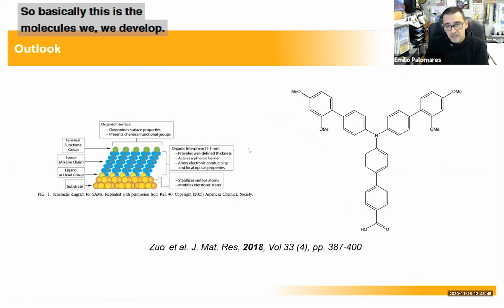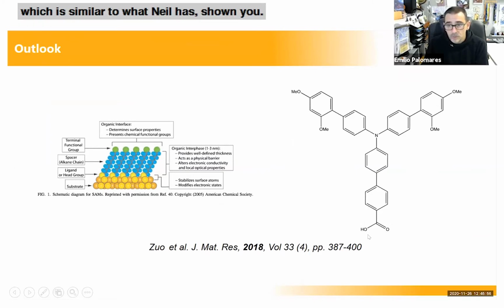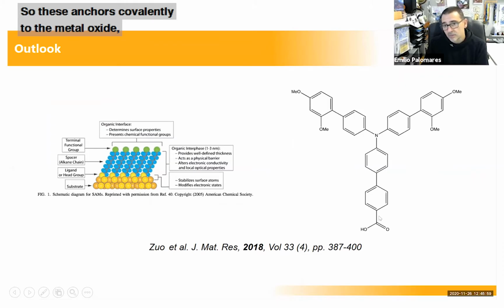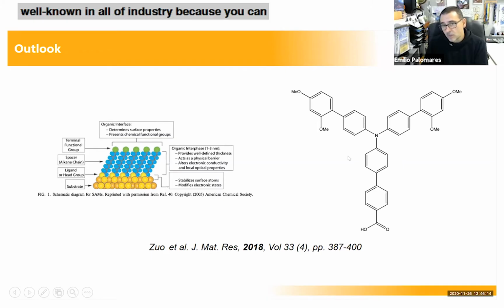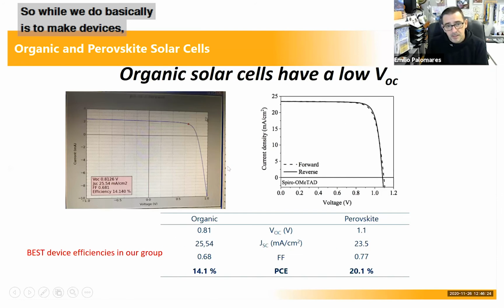So basically, these are the molecules we developed. You have here the carboxylic group, which is similar to what Neil has shown you. This anchors covalently to the metal oxide, as I said, FTO or ITO. You have this alkane, or in this case, these two benzene rings, and then you have a triphenylamine group here with methoxy groups. Basically, this molecule is well known in the OLED industry because it can conduct electronic holes very well with highest mobility. So what we do basically is to make devices.